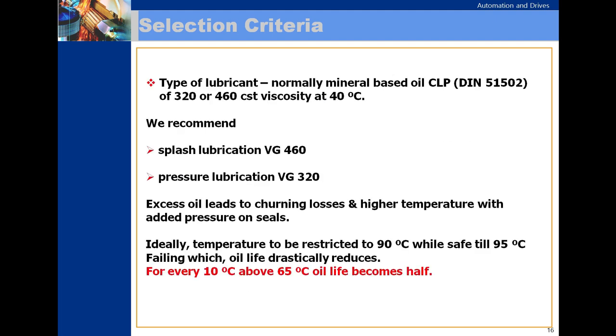Types of lubricant: normally mineral based oil of 320 or 460 viscosity at 40 degrees centigrade. For splash lubrication, 460 VG viscosity oil, or for pressure lubrication, 320. Excess oil leads to churning losses and higher temperature, with added pressure on seals. Ideally, temperature is to be restricted to 90 degrees centigrade, while safe till 95 degrees centigrade, failing which oil life drastically reduces. For every 10 degrees above 65 degrees, oil life becomes half.